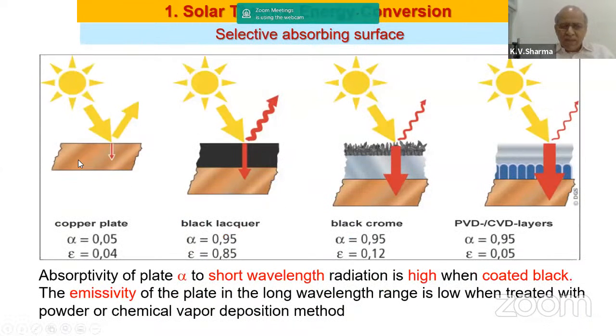Further looking into the absorber plate, if it were to be just a copper plate, we have the absorptivity to be less and emissivity is also low. However, when we go for certain special coatings on these absorber surfaces, most of us must have seen a flat plate collector, and this flat plate collector is generally, when we look at it, black in color. So if it is coated with lacquer, its absorptivity is very high. It has gone up from 0.05 to 0.95. So the absorptivity increases very high. However, the emissivity, it also once again radiates energy back into the atmosphere, which is not advantageous to us.